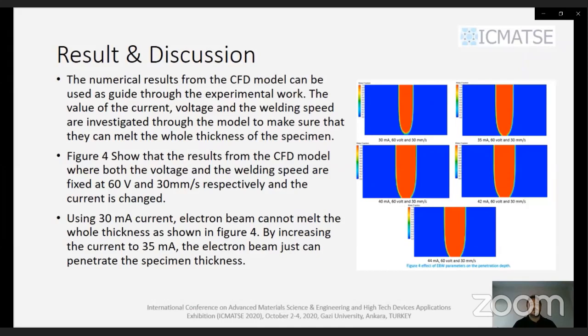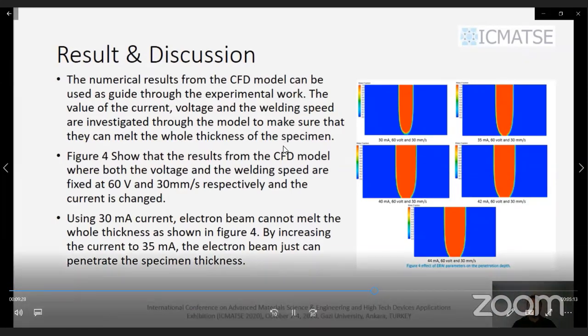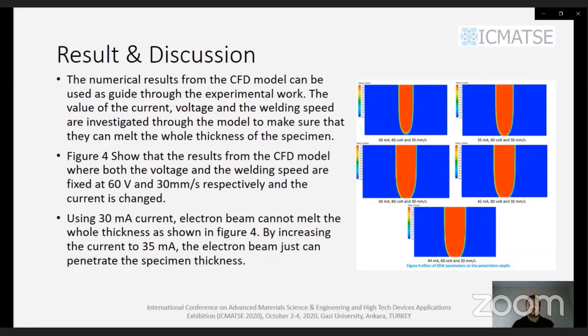So, results and discussion. The numerical results from the computational fluid dynamics model can be used as a guide for the experimental work. The values of the current, voltage, and the welding speed are investigated through the model to make sure that they can melt the whole thickness of the specimen. Figure 4 shows the results from the CFD model where both the voltage and the welding speed are fixed at 60 volt and 30 millimeters per second respectively, and the current is changed. Using 30 milliampere current, the electron beam cannot melt the whole thickness as shown in figure 4. By increasing the current to 35 milliampere, the electron beam can just penetrate the specimen thickness.